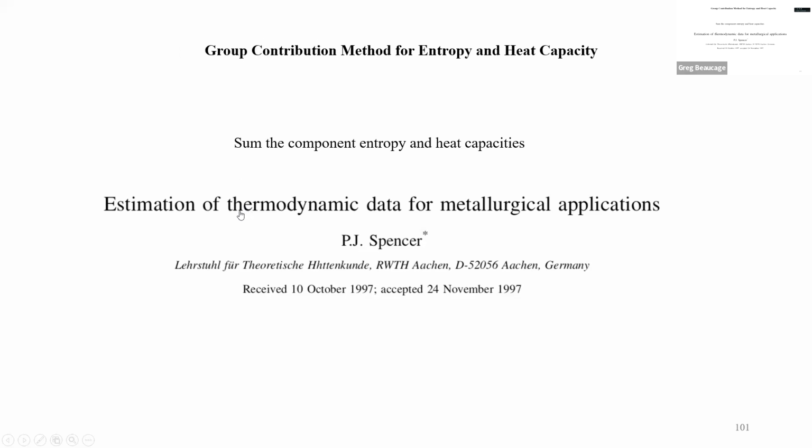Materials, especially organic materials, are made up of groups. If you have some complicated molecule that you made and you want to know the heat capacity of it, you take each of the chemical groups and sum up the components weighted by how many there are, and get the heat capacity. It works pretty well. I mean, it's ignoring most of the science of it, but these guys are in Germany, and the original people that did group contribution were Dutch industrial people, DSM people.